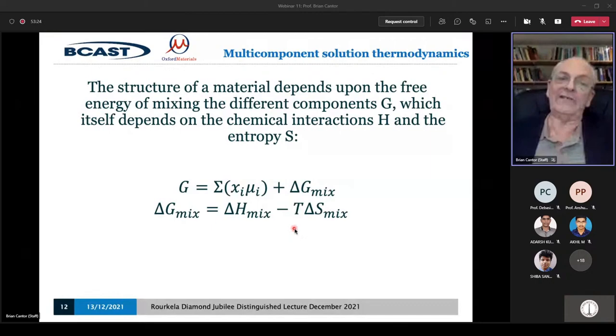So in binary and ternary systems, once you start to alloy a bit, you start to form compounds. At first, that's good. You know, copper, you start to add tin, you get bronze. Then the bronze has a small amount of a compound, the copper-tin compound, which gives it its strength. In the iron-carbon, you learn how to control the cementite to give it its best strength in steel rather than in cast iron.